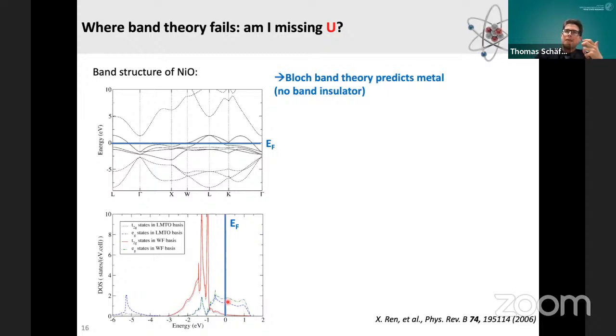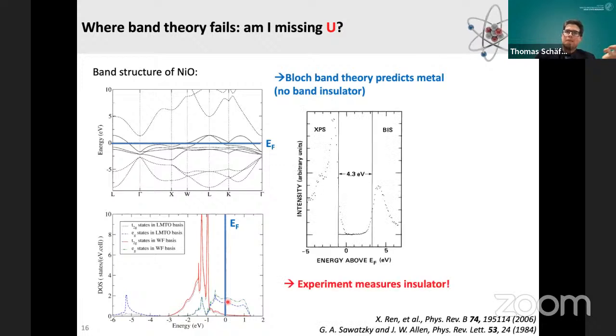However, the problem is now, if you do really the experiment on this compound, what you see in the density of states is that you get a gap at the Fermi level. So you don't get states, but you have a separation at the Fermi level, the so-called gap. So the experiment sees that this compound actually is an insulator.